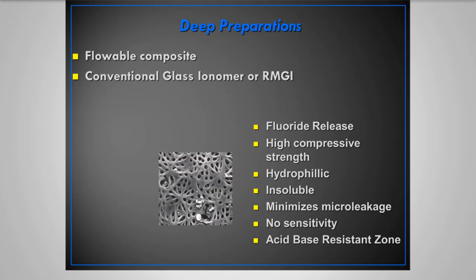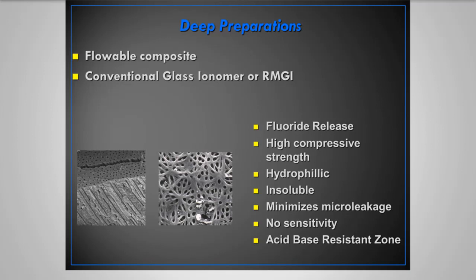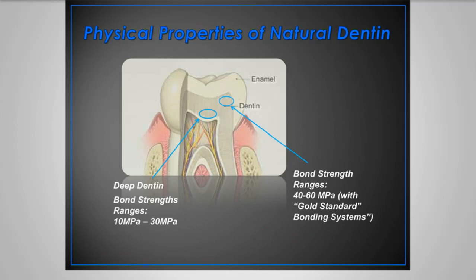Now, you also get a wonderful side effect of having an acid-base resistant zone. It makes this dentin a lot more hypermineralized and more resistant to microleakage problems, whether it be acid insults or future decay. It's a lot more difficult when it's already had glass ionomer on it because it's hypermineralized and has this acid-base resistant zone. So whenever we're superficial in dentin like this or on enamel, I think composites and resins are great materials. But you have a lot more problems when you're deeper inside the tooth trying to adhere to dentin. And that's why I think maybe having a different product in these deeper areas followed by a bulk fill composite on top of it may be more advantageous when you're in these deeper areas.